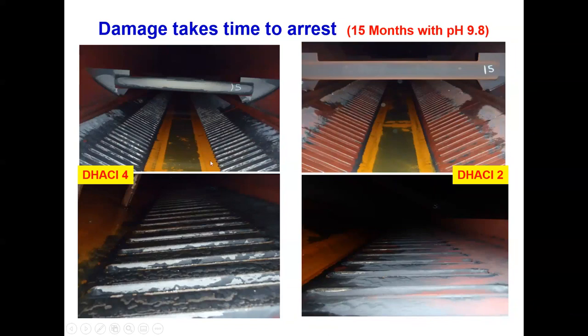After 15 months of operating with a higher pH, you can see the white areas originally, and what they look like after increasing the pH, and the DHACI index decreases as expected. You can see that the white areas have disappeared. In fact, they formed magnetite, and then during the shutdown process, they get this red coloration. On the cross members, you can see that magnetite has formed here, in agreement with what you would expect.